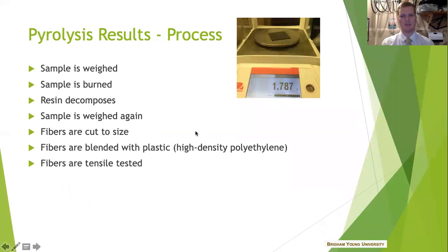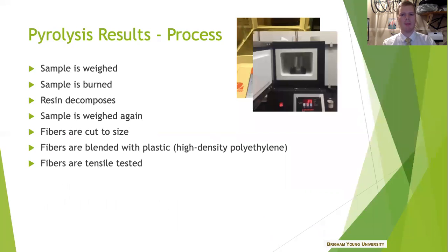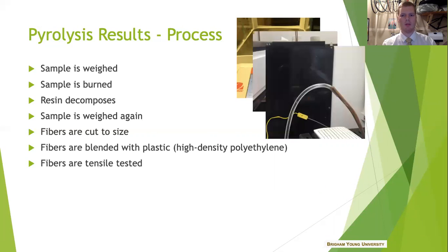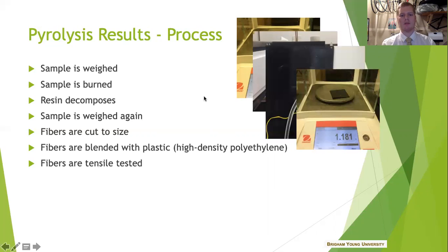So first thing that I did was I cured a bunch of these small little carbon fiber samples. They're about 2 inches square and a 2-ply stack of just some pre-preg that we had left over in our lab. After I weighed them, I would burn them in my combustion chamber that I just talked about, and the resin would slowly off-gas. You can see some of that coming out of the vent tube. Then I would weigh the fibers again and see how much came off. And typically it was a pretty sizable amount, about 40% weight reduction was the most that I saw. So a lot of the resin was burning off.